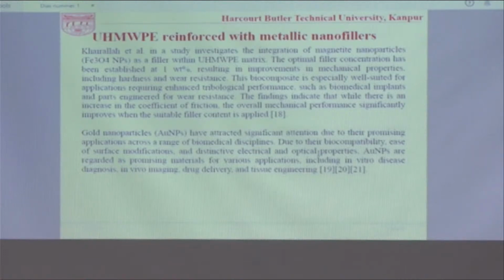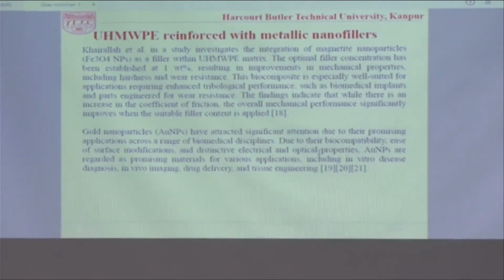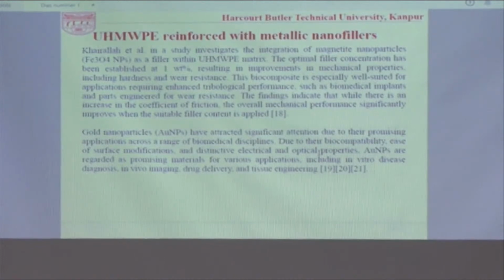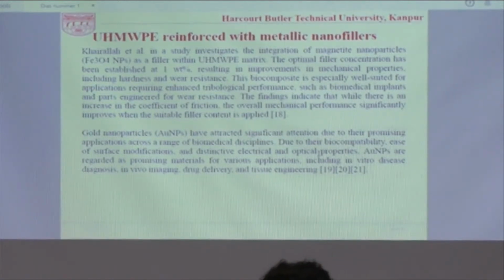These are the latest surveys of the metallic-based nanofillers reinforced with UHMWPE. Recently, a published study shows that with UHMWPE filled with magnetic nanoparticles, the incorporation of 1% of the magnetic nanoparticles improved the mechanical characteristics such as hardness and wear resistance. Also, the biocompatibility has not shown any harsh result, and this material with the incorporation of iron-based magnetic nanoparticles can be used for biomedical settings.